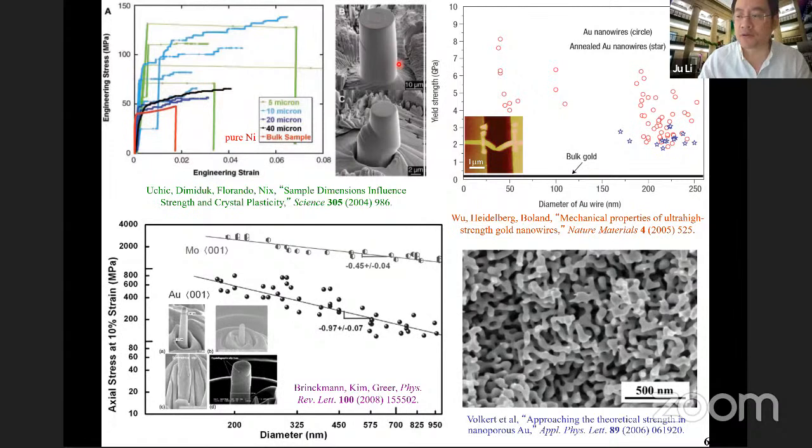Remember, it needs two pinning points. So those pinning points actually are not completely immobile. Due to the image attraction, they are very easily swept out of the lattice into grain boundaries or surfaces. And so you turn more to a defect nucleation controlled strength.